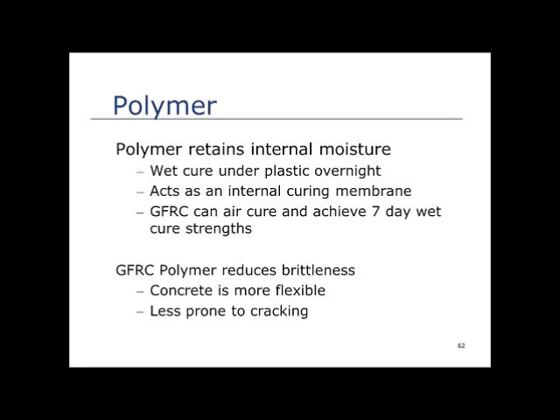With polymer, once that piece cures overnight in the mold, it can be stripped out, and the polymer has now coalesced to form an internal curing membrane, if you will. It's not really a membrane, but it plugs a lot of the pores, lowering the porosity, keeping the moisture in there. So those pieces can be set outside and air cured, and at the end of 7 days of just air curing, they still have the exact same strength they would have had if they had been wet cured for 7 days. So that's the huge advantage of polymer, and that only happens if you use the right amount of polymer and the right kind of polymer.